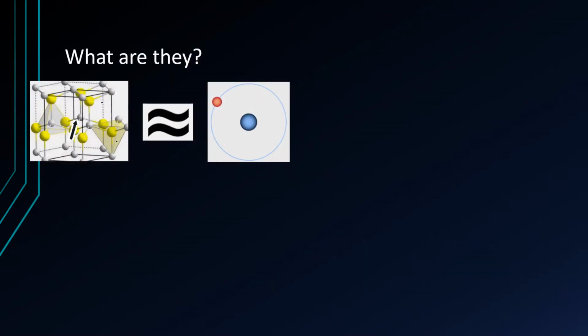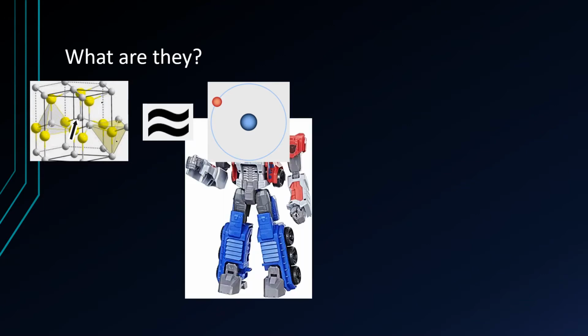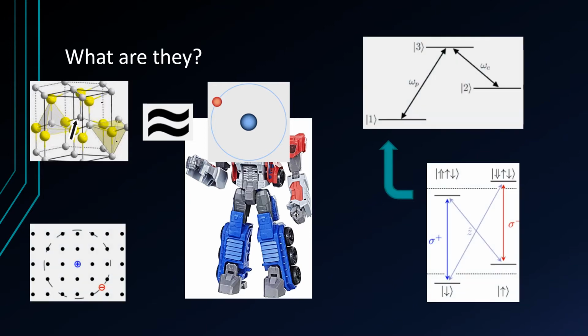But what are these qubits? Donor spins in zinc oxide function in many ways like a hydrogen atom with extra hardware attached that helps with physical confinement, initialization and readout, and of course decoherence. In a practical model of the donor level structure, the two lowest states are the up and down of the donor electron, but there are also two higher states corresponding to an exciton bound to the donor. The exciton consists of a spin singlet with spin 0 from an electron that joins the donor electron, and the hole that electron leaves behind. The hole has spin half, like the electron. In the presence of a magnetic field, this makes for 4 distinct energy levels.